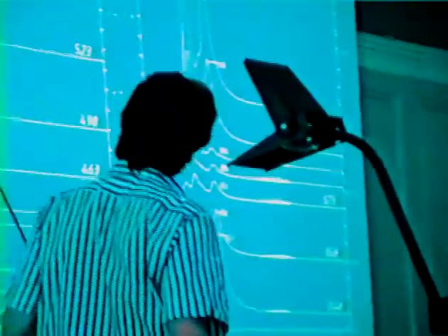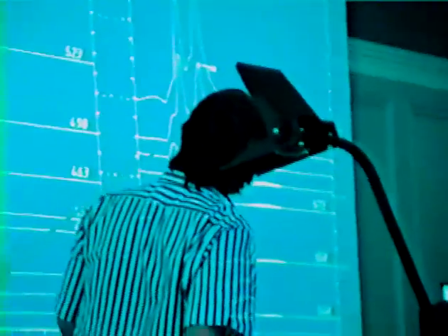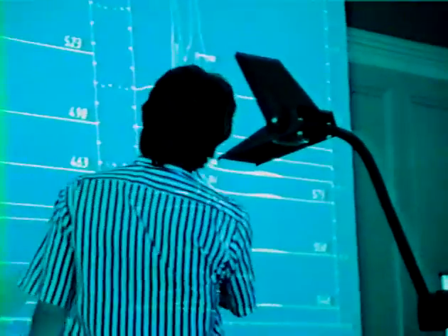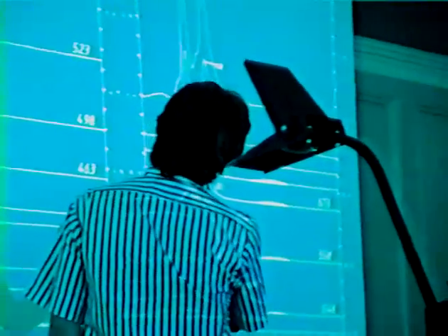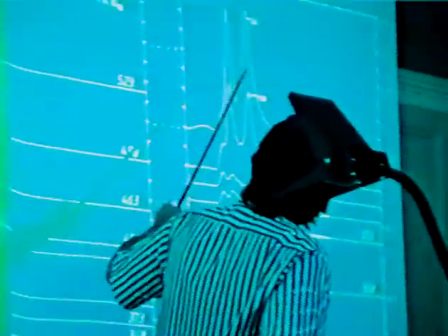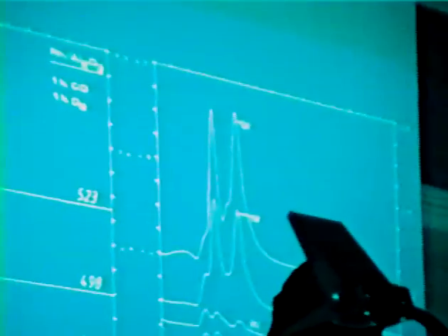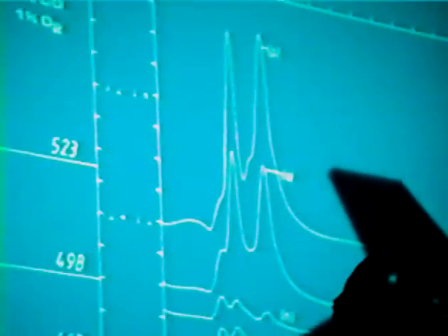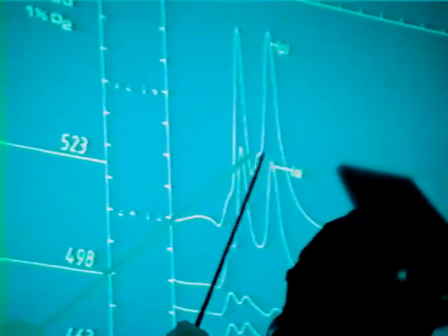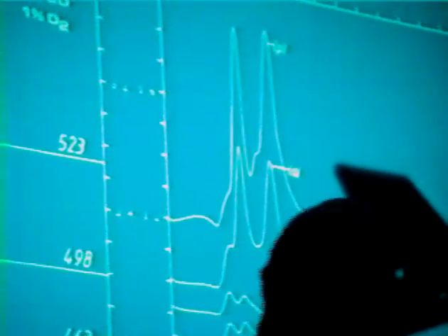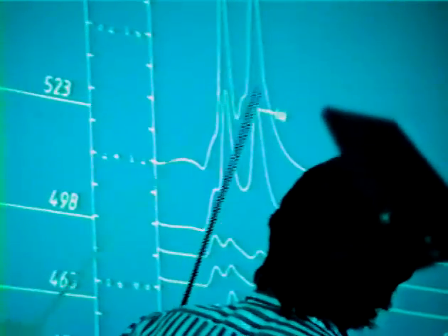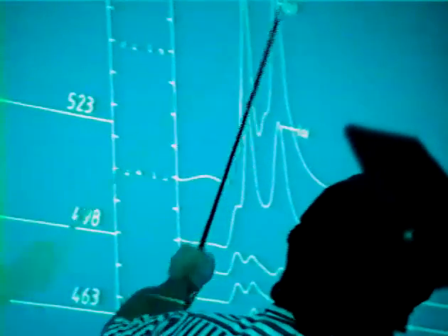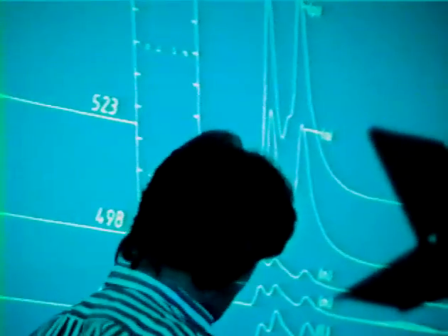You can see that, in contrast to the second slide I've shown, there is a rapid regeneration of the dicarbonyl species. If you leave this as a function of time at 573 K in CO and nitrogen, then we begin to produce the linear carbonyl. If I leave it for a further length of time, then essentially we eliminate the dicarbonyl species and end up with just a linear carbonyl.